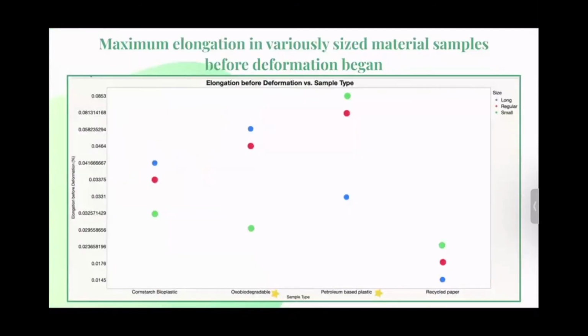Results from the tensile tests were staggered but consistent in regards to the means of percent elongation before deformation and overall strength. Necking occurred in materials that are able to stretch as the force pulling the material apart goes to the material molecule slipping. For my experiment, the oxo-biodegradable plastic and the petroleum-based plastic necked, which is indicated by the yellow stars. From the three different sized pieces of each material, tensile strength was determined through the mean percent elongation before deformation and the mean maximum strength. Deformation is when the first molecules of the material begin to break.